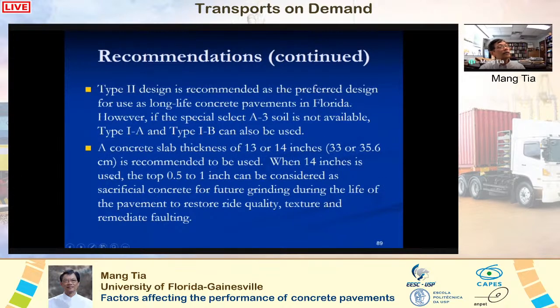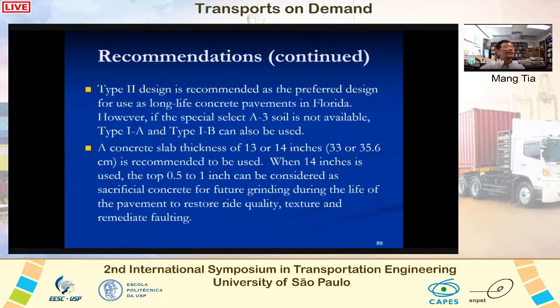Okay, so the key thing is to have enough thickness. If we want it to last for 50 years with heavy traffic, you need at least 13 inches. Better yet, if we have 14 inches. Okay, 13 inches would be equivalent to 33 centimeters, and 14 inches equals 35.6 centimeters. If we use 14 inches, we have an extra either half an inch or 1 inch, which can be considered as sacrificial concrete for future grinding during the life of the pavement to restore its ride quality, texture, and remediate faulting.